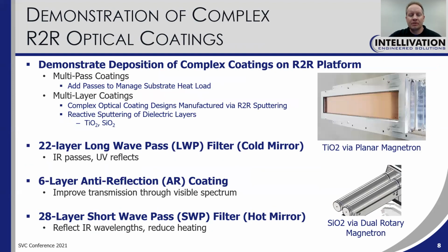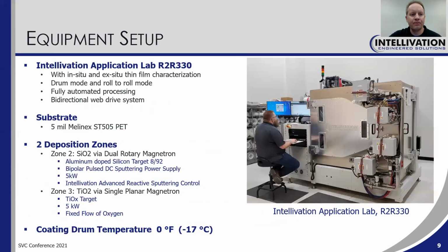So we're going to demonstrate some complex roll-to-roll optical coatings, and we're going to do this on a roll-to-roll platform. We're going to use a multi-pass approach. We're going to add passes to manage substrate heat load in some cases. We'll demonstrate that. And we're going to use TiO2 and SiO2, the TiO2 via planar magnetron, SiO2 via dual rotary magnetron. We're going to look at a 22-layer long wave pass coating, and a 6-layer anti-reflective coating, and a 28-layer shortwave pass coating, or hot mirror.